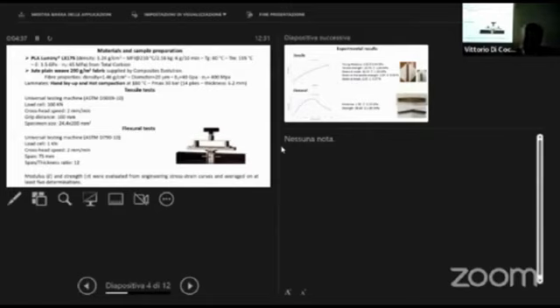We tested the specimens, which were cut directly from the plates that we obtained with this technique, to obtain specimens for tensile tests and for flexural tests. And then we compared the experimental results with the theoretical results, and we see that there are high discrepancies between these data.